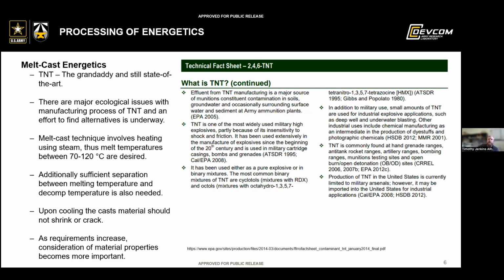So in order to be a melt cast energetic, you have to hit a couple key takeaway points. And one of them is that you have to have a melt temperature. It's very desired to have this between 70 and 120 degrees C. This is because a lot of the processing that we want to do for safety aspects is we want to do it in a steam heated kettle. So 100 degrees C melt temperature is ideal for that. So this range gives us a little bit of room to play with.